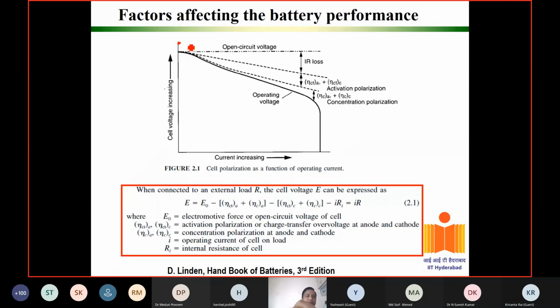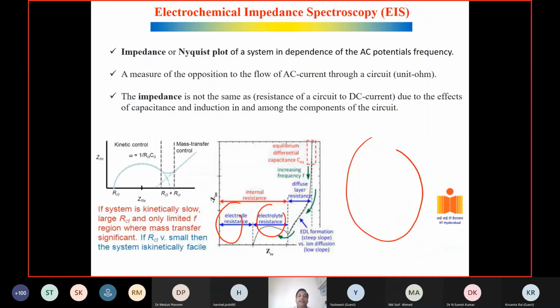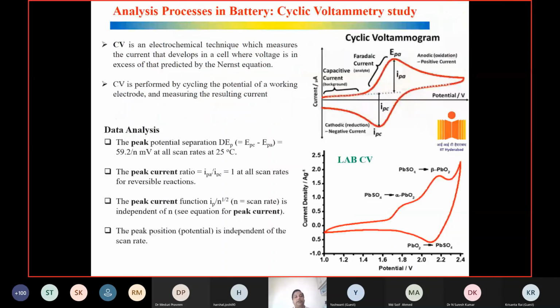Suppose it is a lead-acid battery. As soon as you put the current load, you will have a fast drop, correct? So with the voltage and the current, I equals V by R, you can easily calculate the resistance. This is approximate, but you get it without impedance measurement. For a lead-acid battery it should come in milliohms, whereas in aqueous and non-aqueous electrolytes it will come in ohms. It should be less than even 50 milliohm, and for the battery industries it would be still lesser because their assembly is much better.